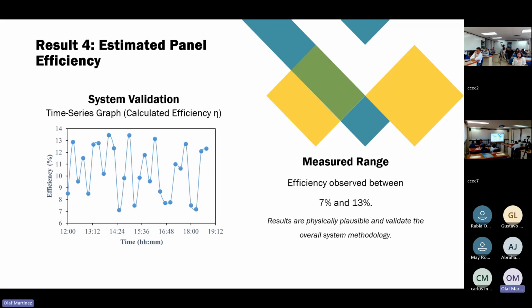Finally, our sixth figure shows the instantaneous panel efficiency, calculated over time using equation 7, which is the efficiency formula. The calculated efficiency values remain realistic for the small solar panel under test, ranging approximately between 7 and 13%. The fluctuations observed are expected due to varying cell temperature and atmospheric conditions. The fact that the calculated efficiency falls within this physically plausible range confirms the overall efficiency of our integrated system and the reliability of our methodology.